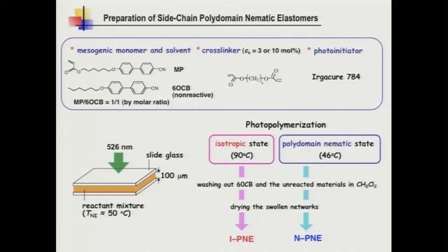Okay, this is a recipe of our sample. So basic reaction is this one. So monoacrylate mesogen and diacrylate cross-linker. So this part is the dangling from the network backbones. Okay, so for our samples, the network backbone consists of the C-C bond. Okay, so we put this nematic mixture into this glass cell, and the mixture involves the photoinitiator. So we irradiate the light, so reaction starts. So macroscopic networks formed. So after reaction, we carefully remove these slide glasses. We have the freestanding films.